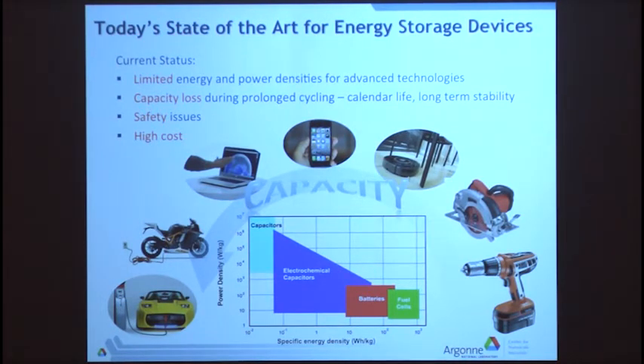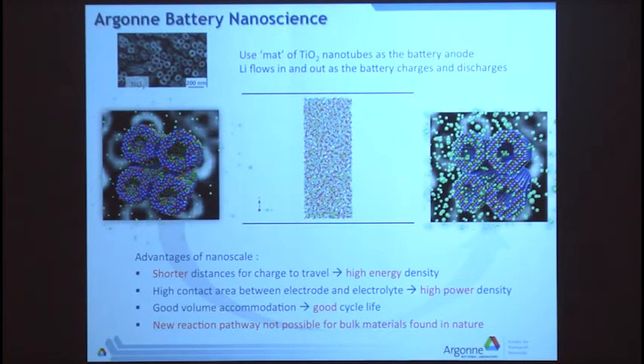And there are all sorts of problems with batteries, and one of them is related to the fact that when you cycle batteries, they get worse. Eventually you have to throw them away. Now, some very interesting research is currently ongoing at Argonne, and that's to use titanium dioxide nanotubes. I've called it a mat because, literally, think of a doormat, those rather bristly, coarse doormats where you've got lots of fibers standing up on a flat surface. That's what the anode of the battery looks like. Each of those fibers is a very small hollow tube of titanium oxide, and it's amorphous, so all the atoms are just randomly arranged. They're not in any ordered crystal structure.